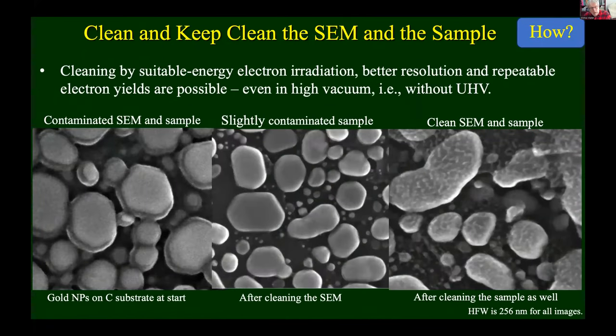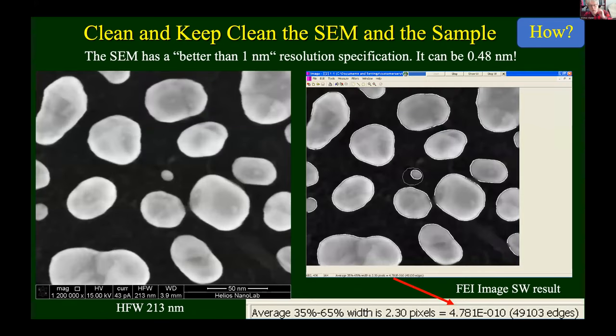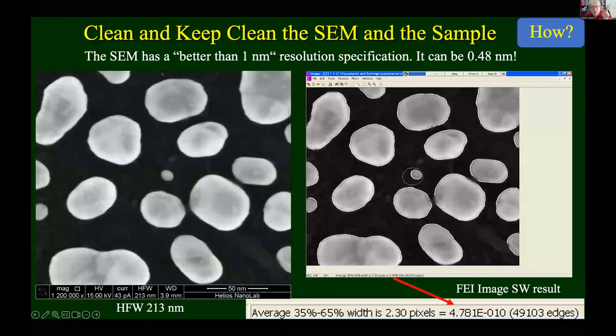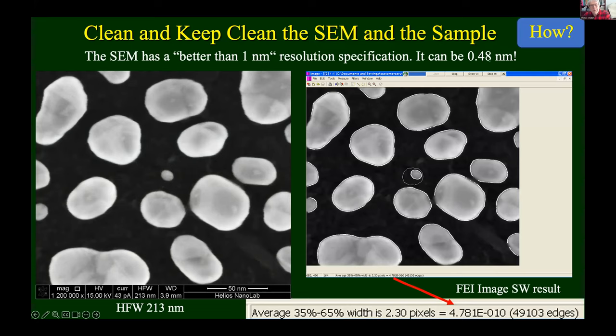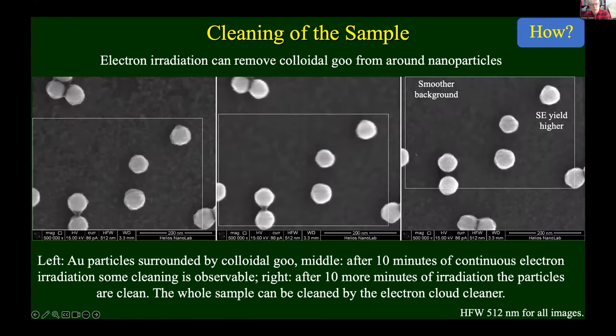Another one is we realized very early that carbonaceous contamination is a critical problem in SEMs. And in the past, it was something people couldn't really do anything about. But we developed methods to make sure that yes, we can measure the sample, not the sample with some unknown amount of carbonaceous material. So these together led to much better performance of the SEM. This SEM has a specification that the resolution is better than 1 nanometer. It can even be twice as good, which is obviously critical for nano measurements. You can see here the fine details on the surface of this tiny object. These are 50, 30, 60 nanometer ones.